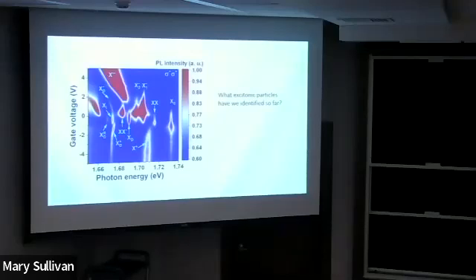Do you know how much strain it's going to induce? Well, I was going to ask you. I have no idea. I notice your X0, your exciton, is moving around from spectrum to spectrum. Sometimes it's close to 1.73, sometimes it's not. Oh yeah, it varies from spot to spot, sample to sample. We think it's a local strain, but we don't know how local that strain is. Yeah, that'll give you an idea of how much you can shift things around, probably 10 to 15 meV. I see.